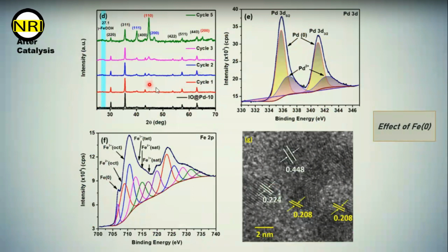As you can see, after every cycle of hydrogen generation, the Fe3O4 peak intensity decreases, and one new peak appears at 44.7 degrees. This is due to iron zero nanoparticles forming in the sample. But how is Fe3O4 forming Fe0? I mean, what is the path of formation of Fe0 from Fe3O4?